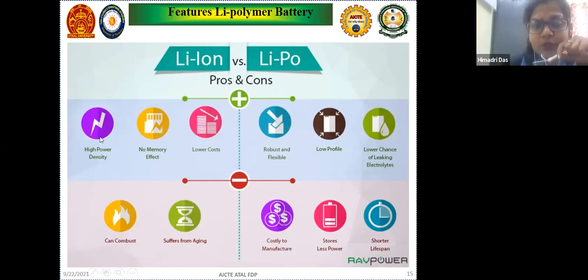Even though lithium polymer based batteries have high power density, no memory effect, low cost, and are robust and flexible, as we can develop flexible devices, and also prevent leakage compared to liquid electrolyte, they suffer from points like the aging effect, high manufacturing cost, storing less power, as well as shorter lifespan. As I mentioned earlier, the polymer can degrade and it is not stable in air also. So these are disadvantages that have to be overcome for the lithium polymer battery.